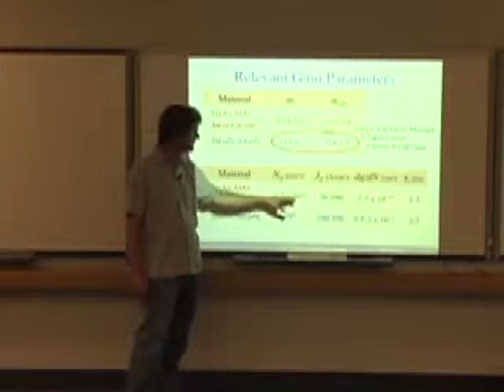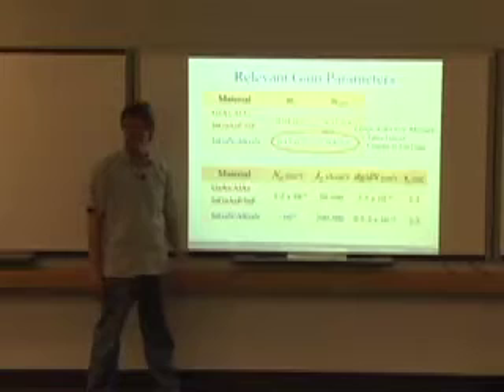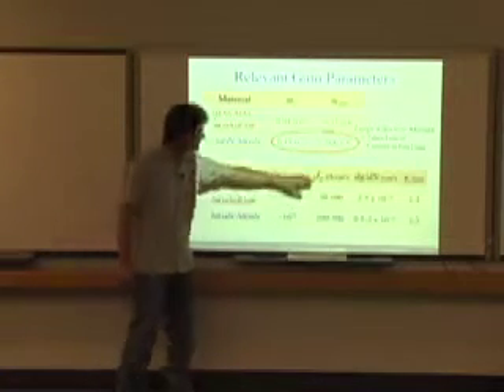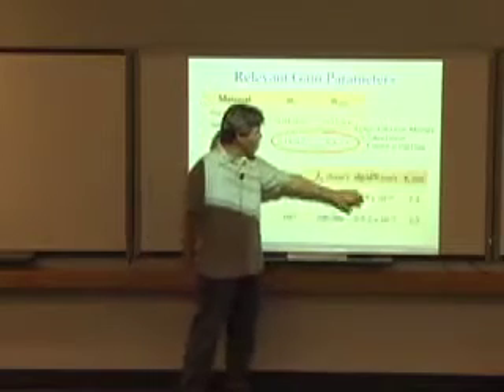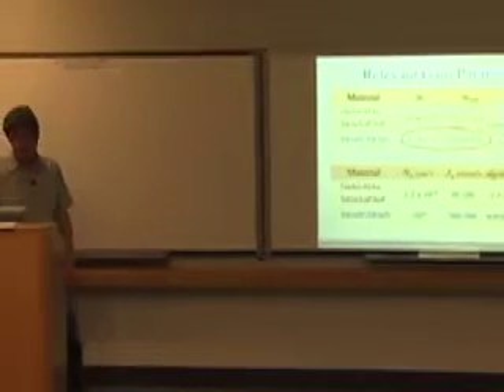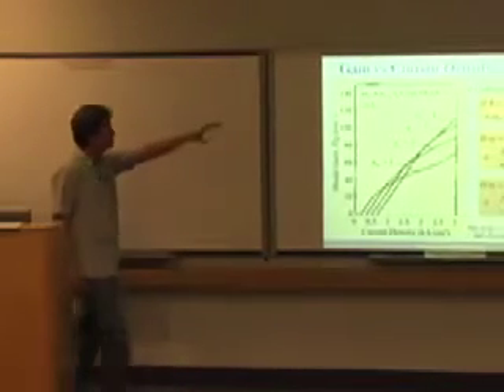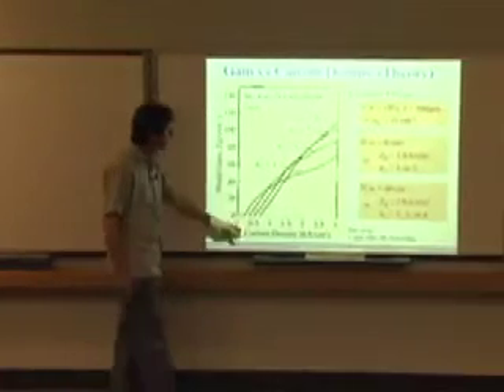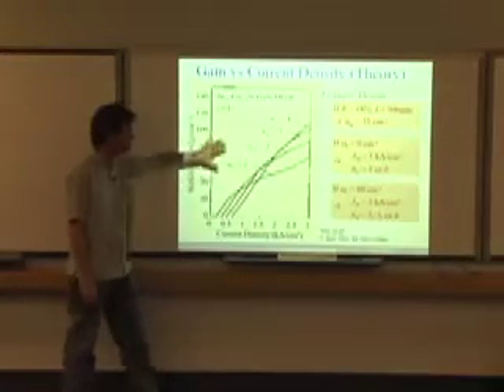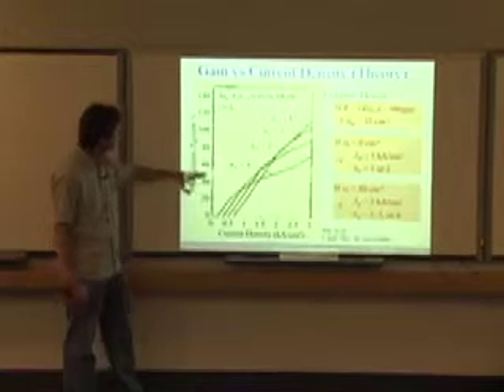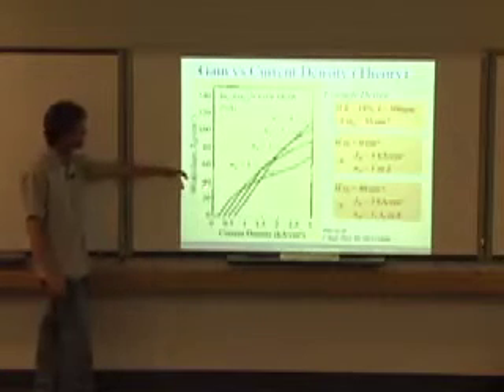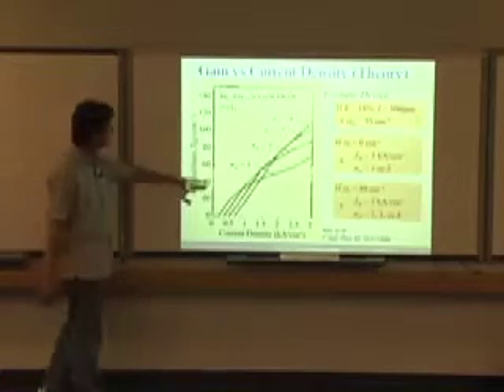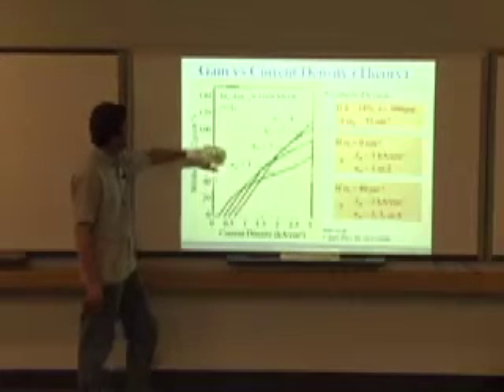Instead of being in 1 to 2 times 10 to the 18th per centimeter cubed, you're talking about 10 to the 19th, probably an order of magnitude, maybe a factor of 5 higher than gallium arsenide. Transparency currents were higher. Differential gain was a factor of 5 lower, perhaps, based on just theoretical estimates. However, even with this, some theoretical estimates of gain show that you can actually get decent gain curves out of InGaN, just from the theory. So 40 inverse centimeters is plenty to get decent lasing if your internal losses are kept low enough.